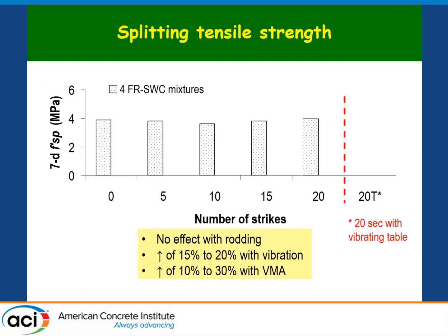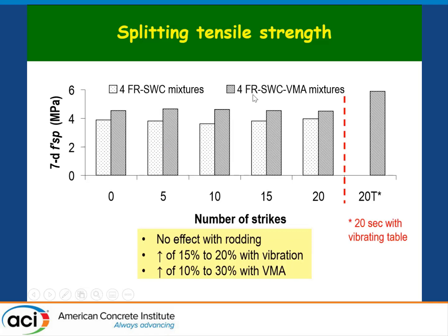So I'm showing here only the splitting tensile strengths at 7 days. And this is splitting tensile strengths of the cylinders without any internal striking versus 5, 10, 15, and 20 strikes. And you can see that the splitting tensile strength is really not changing much. And these are for 4 different fiber reinforced super workable mixtures. And we also had 4 super workable concrete mixture, but in this case was VMA.